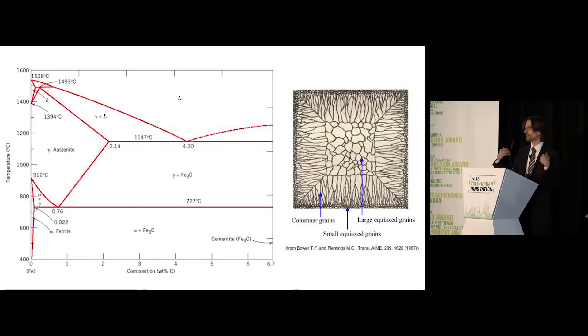As structural steel slabs solidify from the outside in, on the outside we have a very fine grain structure. They're then hot rolled, but only hot rolled in one direction — flattened out like a pancake — which elongates the grains in really just two directions, not three. That works fairly well for thin plate, but when you get very thick plate, you have a difference in grain structure all the way through that plate, and in particular you're going to have different strength in that material orthogonal to the rolling direction.